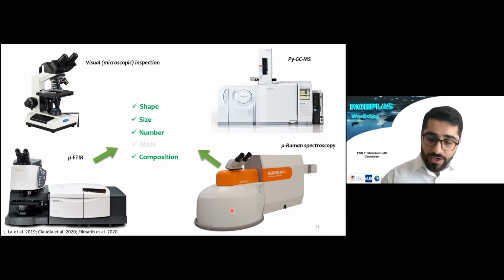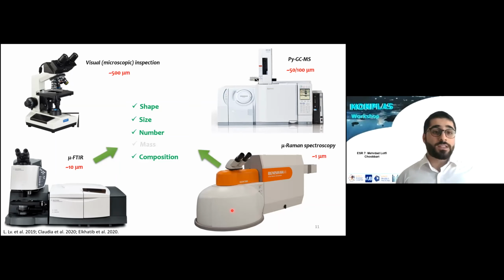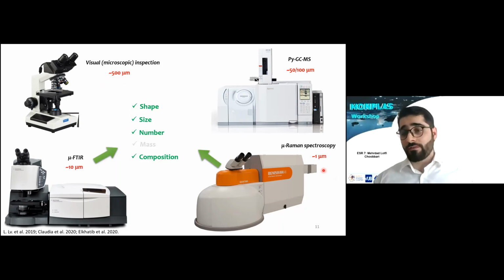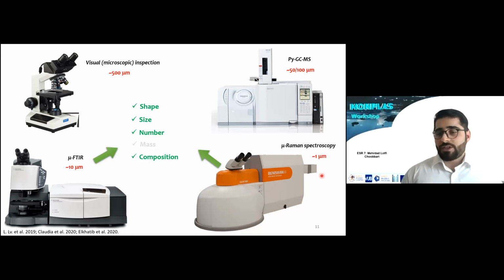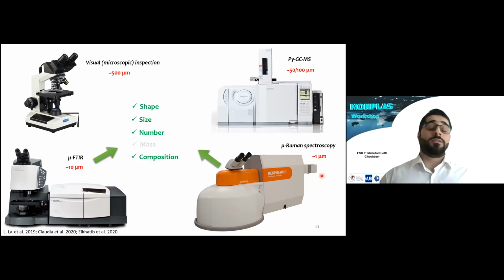The next thing, which is very important regarding each technique, is the size limit of detection. For example, you see visual inspection, as expected, can provide a size limit of detection on the order of 500 micrometer, while micro Raman provides the smallest size limit of detection, which is on the order of 1 micron, and it can even go below 1 micron in some circumstances. But why is it important to consider these parameters, the size limit of detection?